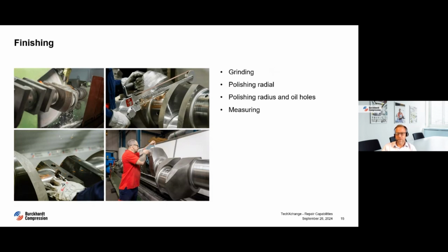The finishing after the laser cladding process is done machined or by hand. The process steps are grinding using a grinding disc. You can see it here. Here's the disc, here's the crankshaft. Polishing by hand. Here we're polishing radial by hand, and also we are polishing radius and oil holes by hand. Here shown on the photo. And the last step was the measurement of all repaired surfaces.